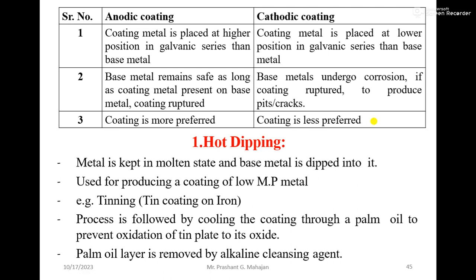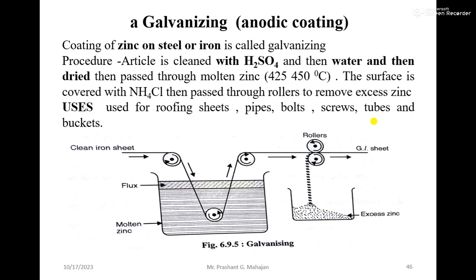The first method of metallic coating is hot dipping — the base metal is dipped in a molten solution of another metal. For galvanizing, molten zinc is kept at 420°C; for tinning, molten tin is kept at 239°C. The article is first cleaned by acid cleaning, then water cleaning, then dipped in the molten metal. Galvanizing is an example of anodic coating.